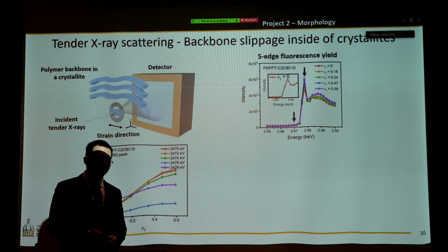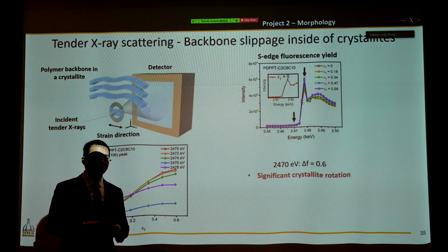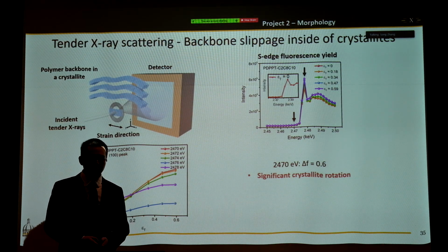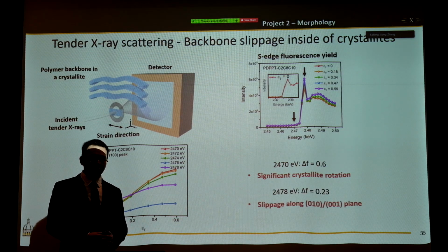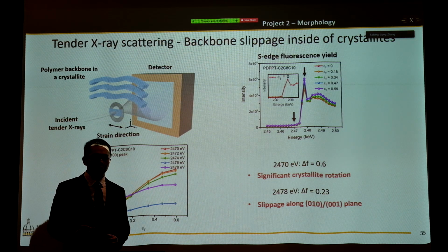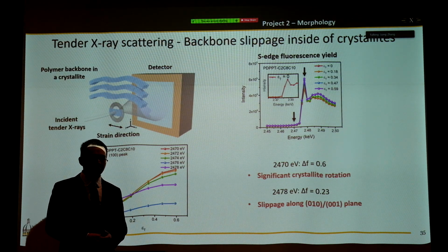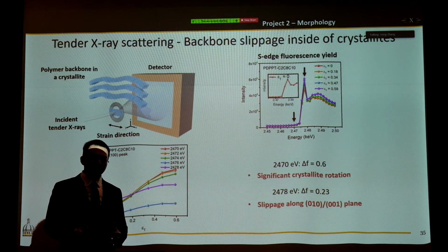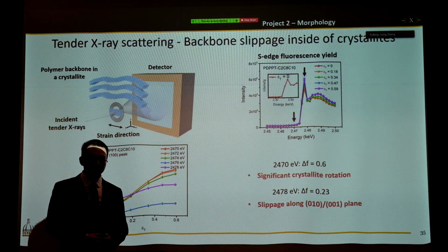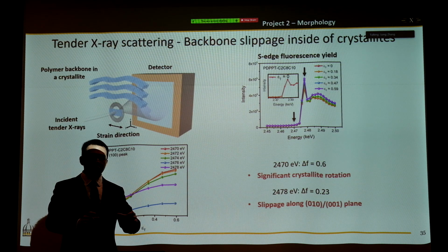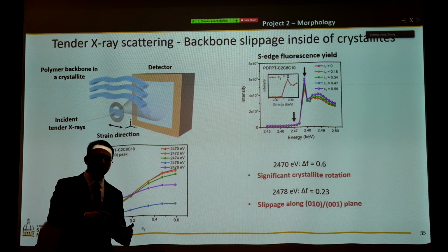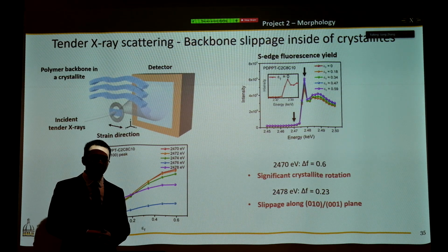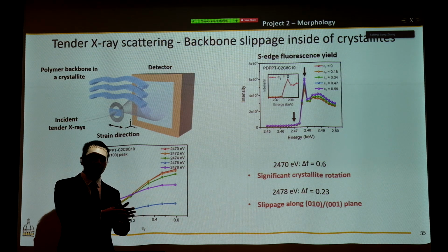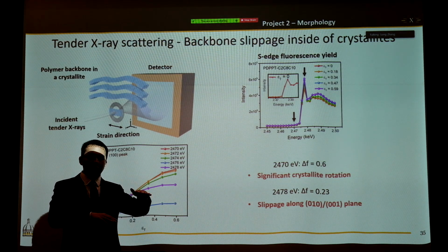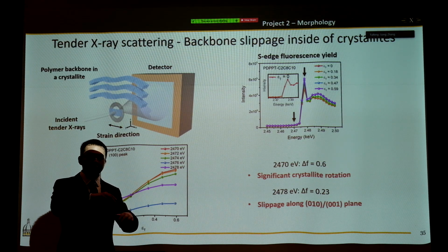2.47 keV gives us a delta F value of 0.6, which is exactly the same as hard X-ray. And that is understandable because at this energy, we are looking at the entire lamellar structure. However, at 2.478 keV, the degree of alignment is significantly smaller when compared with F equal to 0.6. And why is that? Now we think we proved the backbone slippage mechanism we brought up before. Because when the crystallite is aligned, the backbone alignment is smaller than the degree of alignment of the crystallite itself. So the backbone slippage does not only happen from the pi-pi interaction, but also between lamella and lamella due to the van der Waals force between the side chains, which is pretty weak.